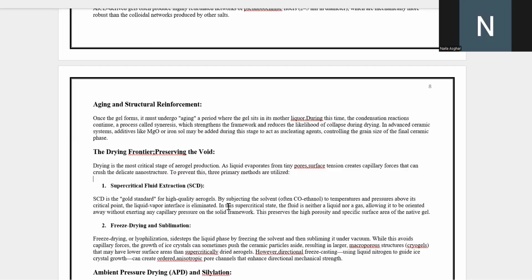The second drying method is freeze drying. The liquid in the gel is rapidly frozen solid. Then, under low pressure, the ice is turned directly into vapor, a process called sublimation. Skipping the liquid phase entirely, this avoids crushing surface tension, but there's a trade-off. As the ice crystals form, they can push the solid network aside, creating larger pores. The result is often a slightly different material called a cryogel, which is still highly porous but may have different mechanical properties.